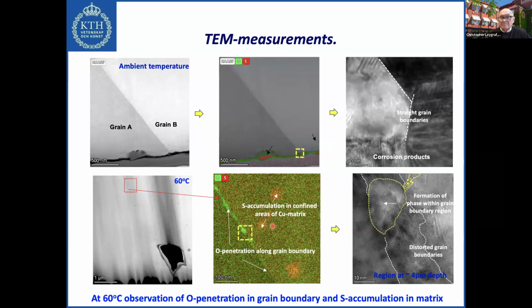We can also see that there is a sulfur accumulation, these red areas inside the grains, not only at the grain boundaries. And if we look further with a much higher resolution, this is 10 nanometers now, we see that this is a whole grain boundary region, which looks like this. It's quite broad, and it is distorted.